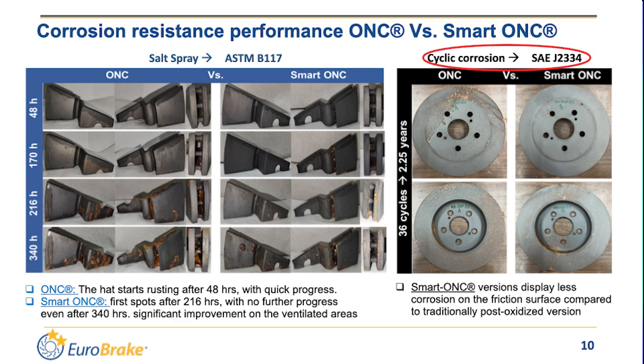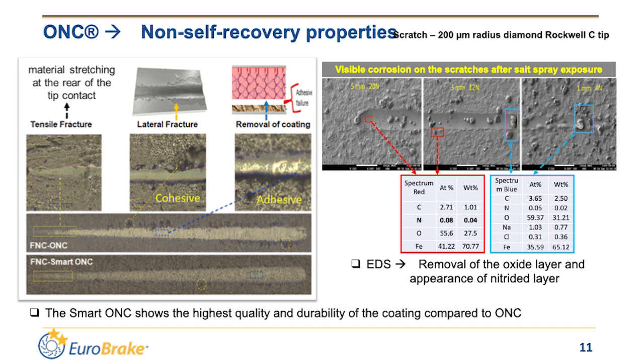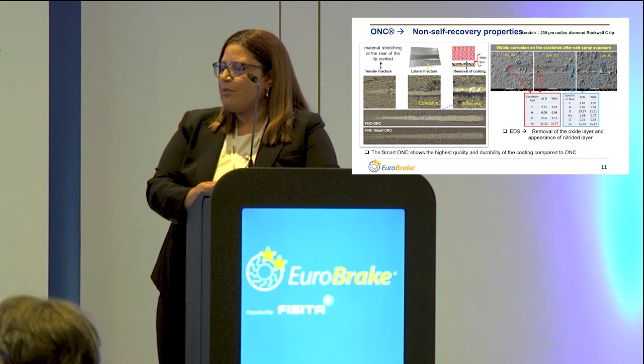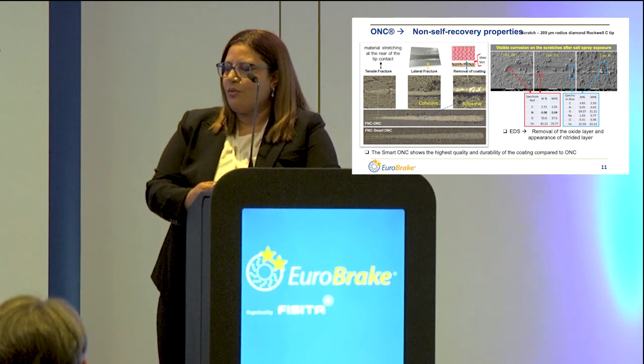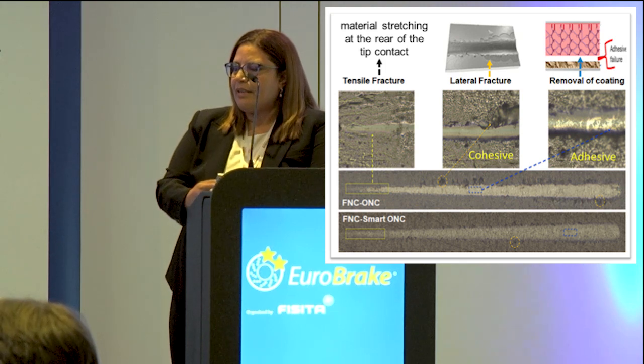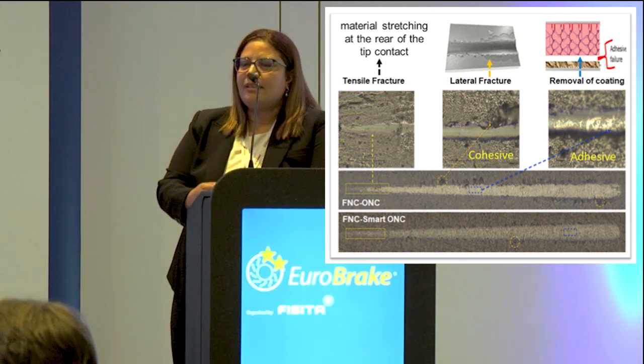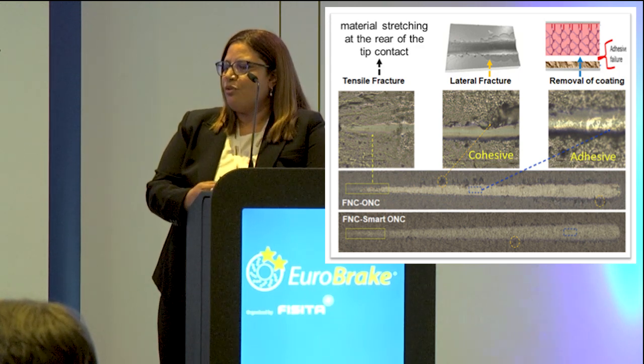We also did cyclic corrosion testing according to the SAE J2334 standard for full rotors. After 36 cycles, we can see that Smart ONC is behaving much better than ONC. To compare the different types of failures and the coating quality, we performed scratch testing on both the ONC and Smart ONC. The different types of failures that we can observe on the FNC ONC include tensile fracture, lateral fracture that happened on the side of the scratch, and the adhesive failures that involve the removal of the oxide layer.